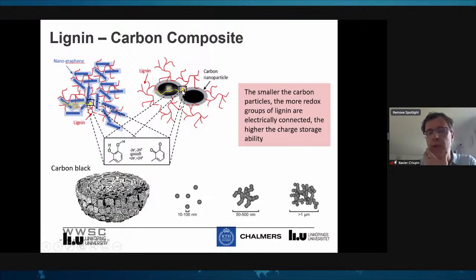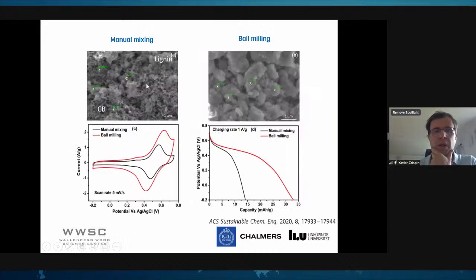So the storage should not be great. So if you want to improve that, you need to break those carbon black apart into small particles to get small particles and better coverage of your lignin. And this is what we have been doing.